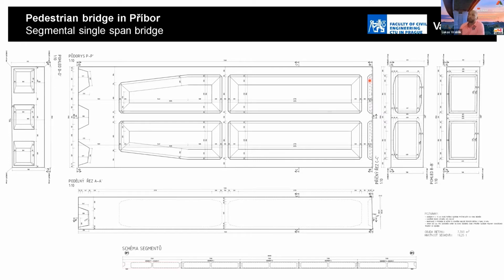What was interesting, because we want to reduce the volume of the concrete, there are big hollows in the superstructure, in the segments. On one side, we want to reduce the volume of the concrete. On the other side, it is impossible to have this hollow in the structure and not be able to make an inspection of this hollow. So we have decided to use polystyrene, so that these hollows were filled by polystyrene members. It was a big challenge, because during the casting, it was necessary to fix the position of these polystyrene members. You will see it on the next slides from the casting of the elements.